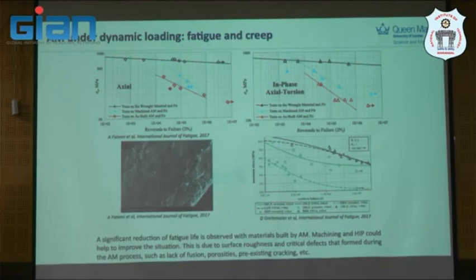So this is what happened. They study this. Why do they need to study this? For example, if this one is actually titanium 6-4 and you want to print it for an implant, I don't think you can do any treatment for the surface. So you may use this implant from a scaffold or whatsoever that you want to use. So that's why you need to keep the surface as it is, right? This may be good for cell growth, but if it's actually AM and you cut it to remove the surface, this will contribute to a different fatigue life here as well.